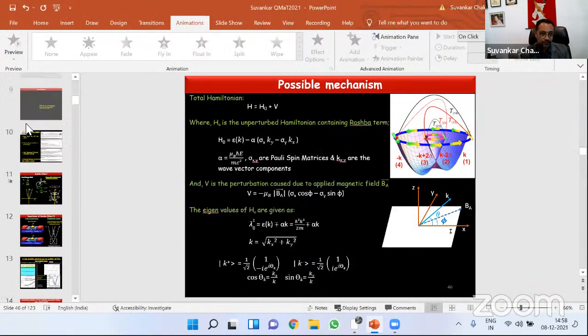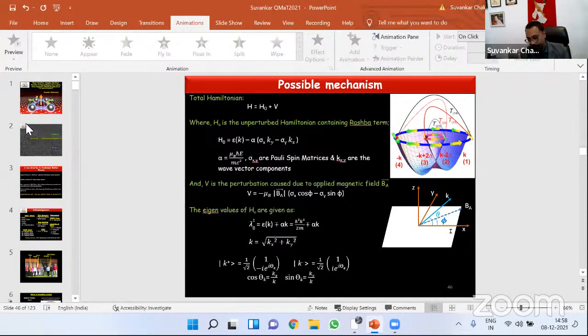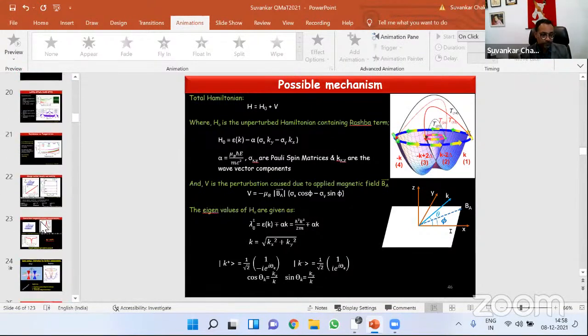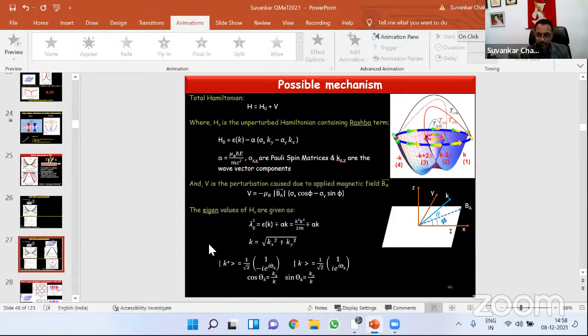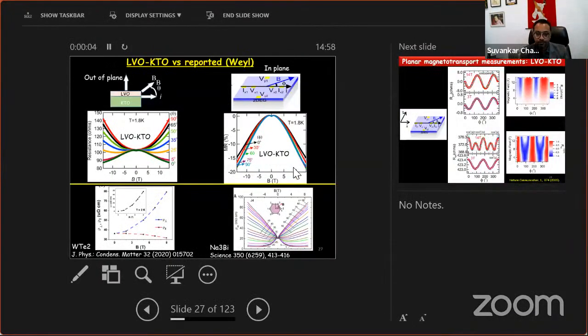Thank you, Suvankar, for a beautiful talk. Very nice work. But I have a basic question. I think your argument about Weyl nature could be questioned a little more carefully, because in Weyl, whatever you call the Adler-Bell-Jackiw chiral anomaly is strictly valid for longitudinal magnetoresistance. And when you showed the plot, when you see the negative magnetoresistance at 5 degree, 25 degree, one has to be a little careful whether there really is any topological aspect to it. I just want to know, because in potassium tantalum oxide, the spin orbit coupling is coming from KTO only, right? So for all this MR, what is the role of the interface between LVO and KTO, rather than focusing on the Weyl part, for which I didn't find direct evidence?